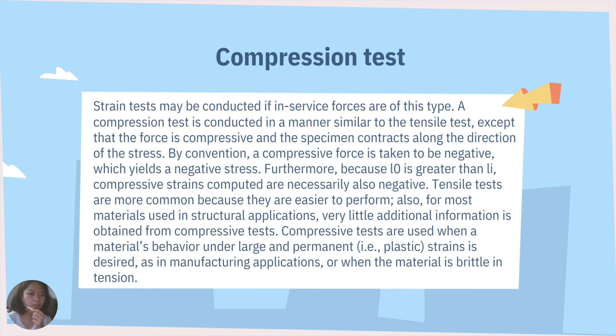For the compression test, compression tests may be conducted if in-service forces are of this type. A compression test is conducted in a manner similar to the tensile test, except that the force is compressive and the specimen contracts along the direction of the stress. By convention, a compressive force is taken as negative, which yields a negative stress. Furthermore, because l₀ is greater than lᵢ, compressive strains computed are necessarily also negative. Tensile tests are more common because they are easier to perform, and for most structural materials, very little additional information is obtained from a compressive test. Compressive tests are used when a material's behavior under large and permanent strain is desired, as in manufacturing applications, or when the material is brittle in tension.